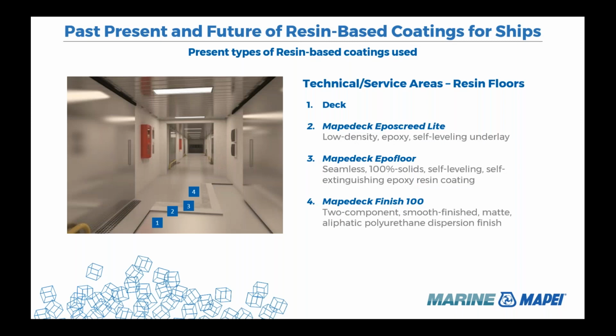This is more or less the same system using a different underlayment, because in the slide before we have used a kind of hybrid system with a cementitious lightweight underlayment. This is instead a full epoxy resin system consisting of an underlayment, which is the Eposcrete Light, epoxy based, 2 component, the top coat, which is the MAPEDEC EpoFloor, 2 component epoxy resin, and MAPEI Deck Finish 100, which is a two-component matte aliphatic polyurethane finish. In this case, there's no need of primer because the epoxy underlayment is very surface tolerant and can be applied on top of the steel deck to level it after a suitable mechanical preparation. Next slide.